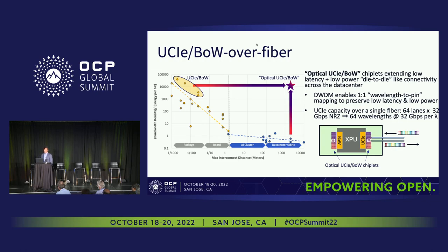Yeah, that's a great question. For us, from our vantage point, obviously this is totally objective, unbiased, the answer is yes, and the reason for that is the quantum dots enable the low RIN nature of the multi-wavelength comb source. We can get into the physics, but basically what it boils down to is if you try to make a multi-wavelength laser in a quantum well, the wavelength lines are coupled to each other, and so there's a lot of mode partition noise, and it'll be difficult to get to low noise per line, which you'll need to close these links with high fidelity. The quantum dots get around that.